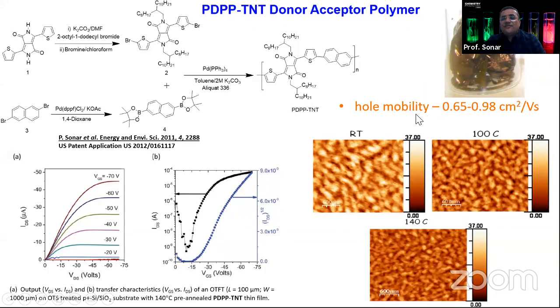That's why you can see we get a hole mobility here, and the hole mobility values are quite high, 1 centimeter square per volt second. This is again the typical curve. We apply the negative gate voltage bias, we get the positive kind of hole mobility, and here are the gate voltage values and how this saturation mobility shows out. This is the transfer characteristics, this is the output characteristic, and the AFM data.